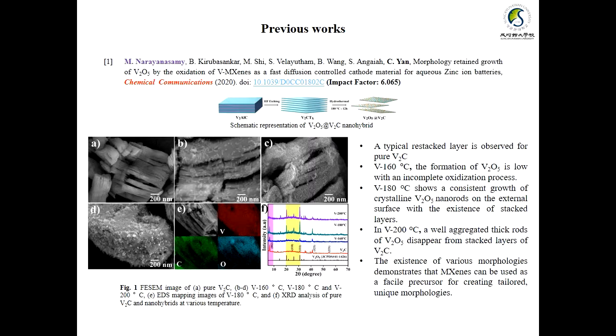The first work describes the morphology-retained growth of V2O5 by oxidation of V2C MXene as a fast diffusion-controlled cathode material for zinc-ion batteries. Here, what I have done is, first I prepared a vanadium-based carbide material, MXene, and I used a hydrothermal heat treatment at various temperatures: around 160, 180 and 200 degrees centigrade.